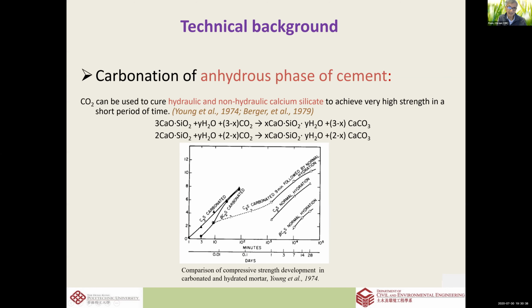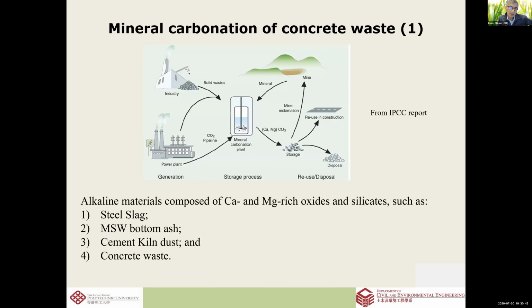And this has been considered as one of the carbon dioxide sequestration techniques. Mineral carbonation is promoted by the IPCC, the Intergovernmental Panel on Climate Change, and it did consider industrial waste, particularly alkaline industrial waste like steel slag, ashes from incineration processes, cement kiln dust or concrete waste. It contains alkaline. This alkaline can be carbonated, and with this carbonation, it can be used to capture CO2 as well as produce a value-added product for other uses like recycled aggregates.